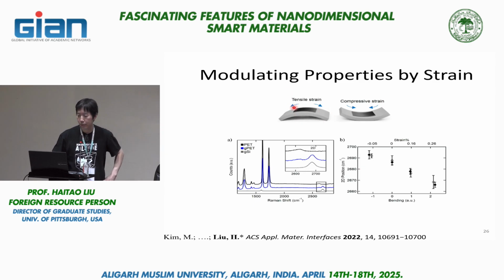So in this set of experiments, what we did is we made chemical vapor deposition grown graphene. We put them onto a polymer substrate. This is essentially a piece of plastic. What we can do then is we can bend them in different ways. And depending on the direction of the bending, we can bend it in this way or in this way. Right? Depending on the direction, we can create a tensile strain or compressive strain. And what we are doing at the microscopic level is we're simply compressing the carbon-carbon bond, or elongating the carbon-carbon bond. Now, if you look at the Raman data here, you can see